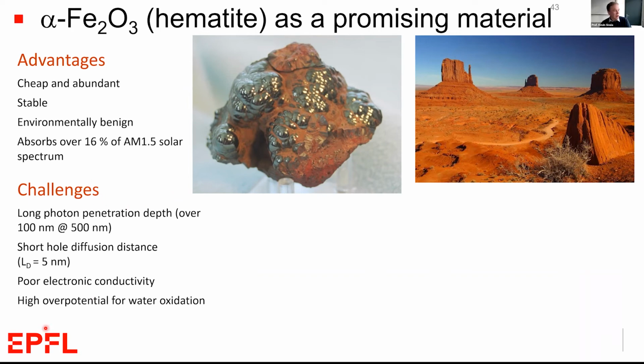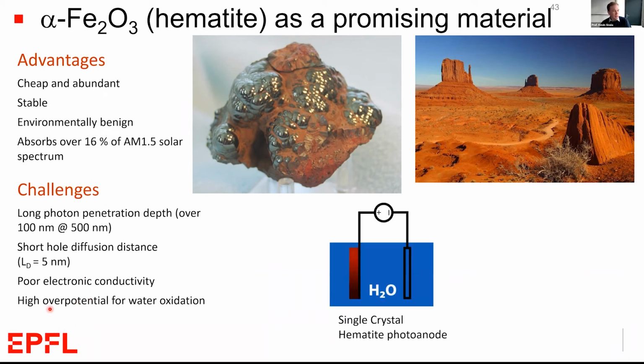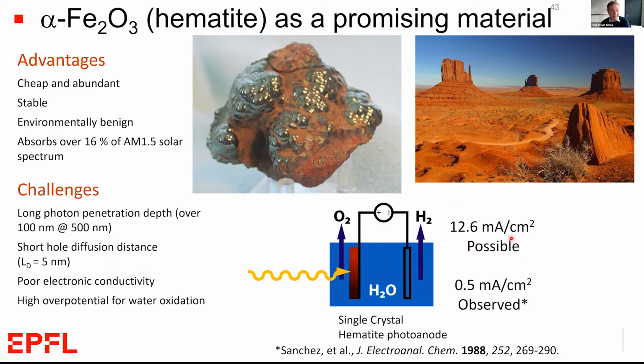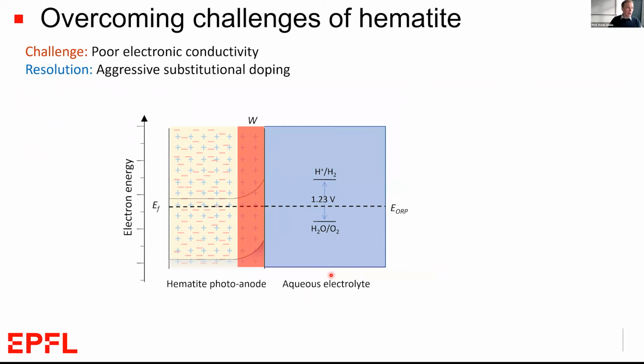However, it's got a lot of electronic problems. And just to summarize this, if we make a perfect single crystal hematite photoanode and we want to split water with it, producing oxygen, based on the amount of light that the crystalline hematite photoanode would absorb, we would expect to see about 12.6 milliamps per centimeter squared photocurrent due to that oxygen evolution reaction. But we only observe about 0.5 milliamp per centimeter squared in these single crystal based electrodes. So one reason for that is the poor electronic conductivity in this hematite.